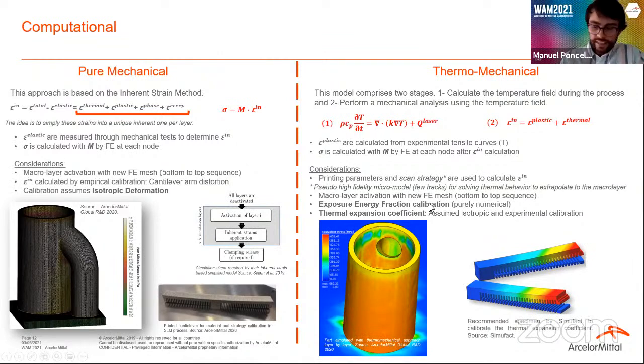Even though the scan strategy is used, because they use it to calculate how much time it takes to print each layer, and also because this model has a pseudo high fidelity micro model, where it solves the thermal behavior with a few laser tracks that it then extrapolates to the macro layer. But it doesn't use the scan strategy, let's say, for performing high fidelity simulations.